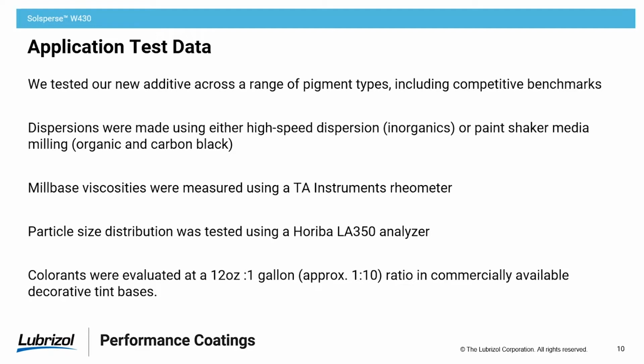Now, when we were making inorganic pigment dispersions, TiO2, iron oxides, we're using high-speed dispersion only, just a Cowles blade. And with the harder to disperse pigments, the organics and the carbon black, we're using a media milling technique on a paint shaker. We measured our viscosities across a range of shear rates using the TA rheometer. We did measure particle size distribution to make sure we achieved a good off the Hegman scale grind. And then we tended to look at mid-tone type tints at a 1 to 10 pigment to TiO2 ratio. In some cases, we looked at lighter tints. And we're looking at tint strength, of course.